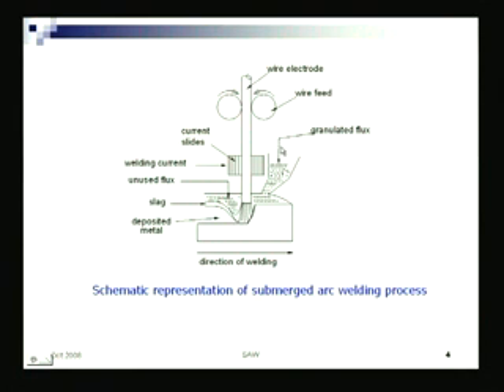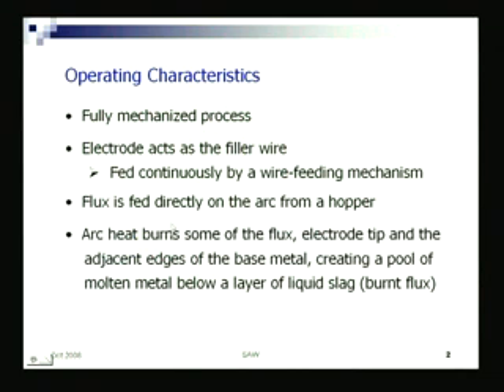Anyway, this is a continuous feeding mechanism, power is fed here through this bush. There is a hopper from where you put the granulated flux. That flux burns and forms a layer of slag, right. So, that arc heat will burn the flux. That burnt flux in the melt is slag.